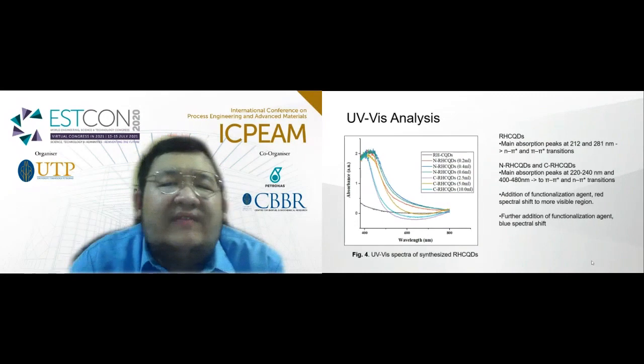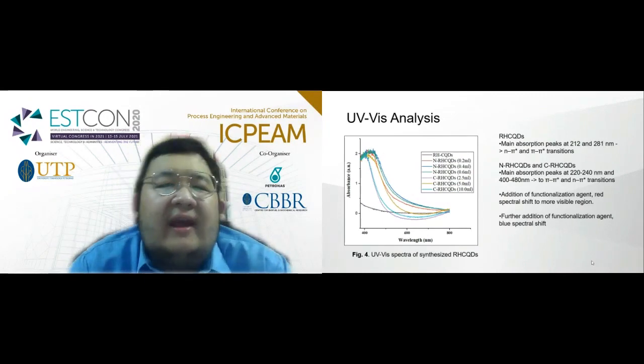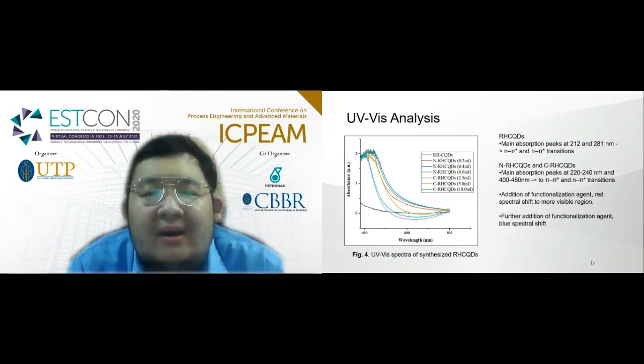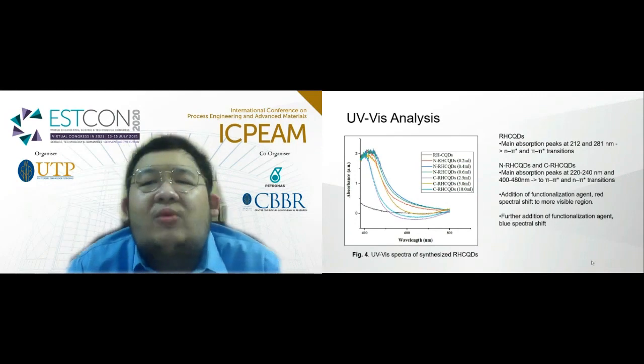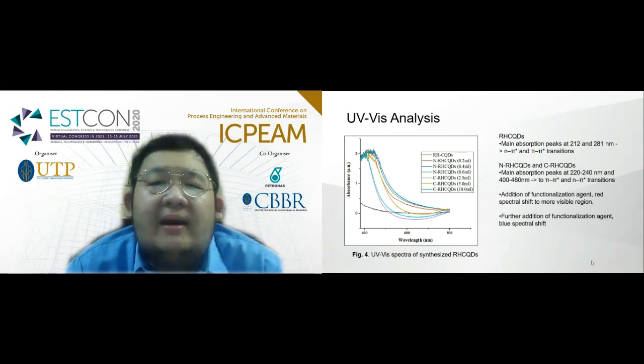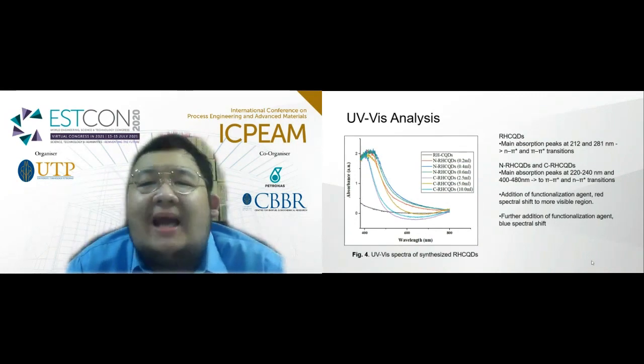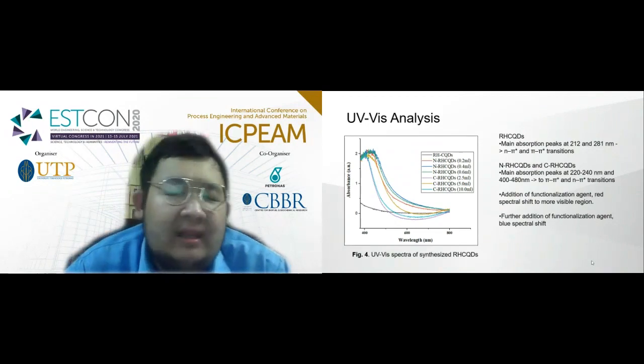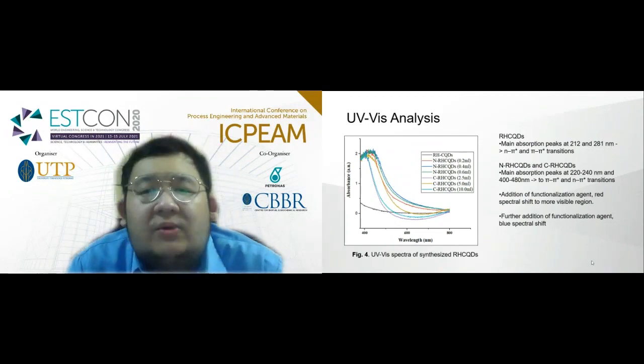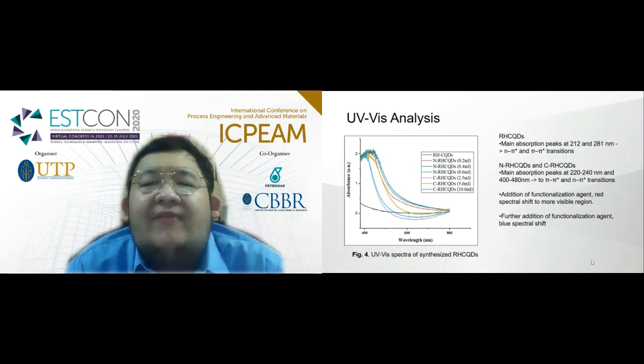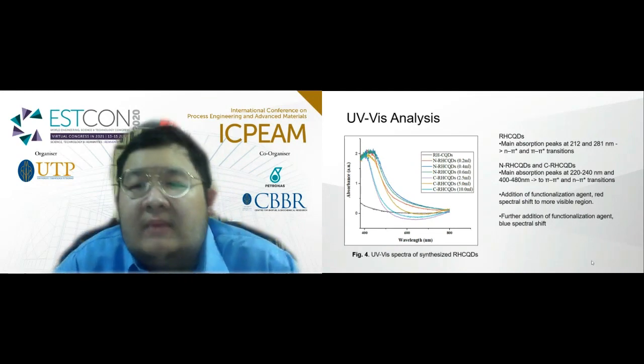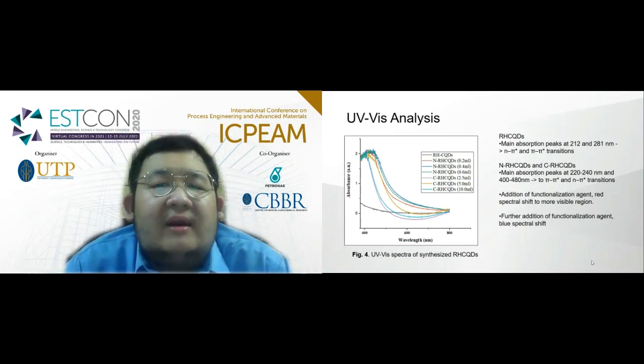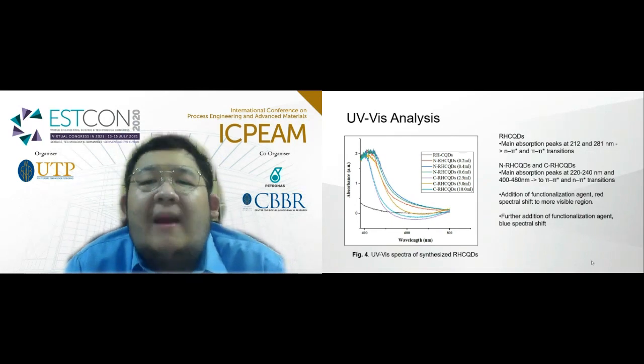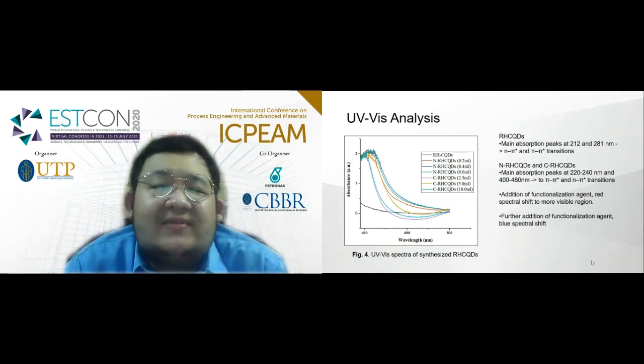Moving on to the UV-vis analysis. In the case of rice-husk carbon quantum dot only, main absorption peaks are found at 212 and 281 nanometers, with respect to n-pi-star and pi-pi-star transitions of C=O bonding. For the functionalized CQD, main absorption peaks are found at 220 nanometers and 400 nanometers, which are due to pi-pi-star and n-pi-star transitions of C=O bonding.